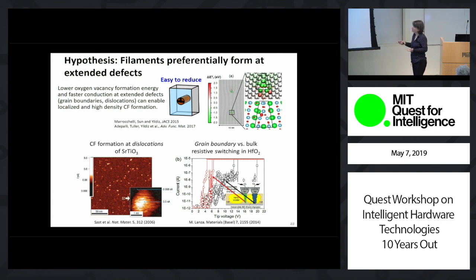And this could explain the experimental observations, for example, for strontium titanate, formation of conducting filaments along these dislocations. If you form preferentially oxygen vacancies along these dislocations, then the n-doped zones also become those filaments where the oxygen vacancies have formed. Similarly, grain boundaries of hafnium oxide were mapped by conducting AFM tip, and the switching characteristics along grain boundaries versus grain interior is different. Higher conducting states and lower voltages could switch to higher conducting states along the grain boundaries of hafnium oxide. So again, extended defects seem to play an important role.